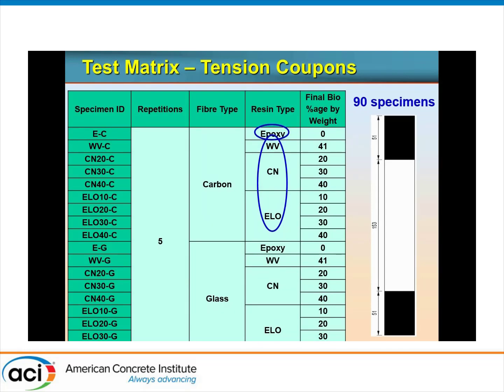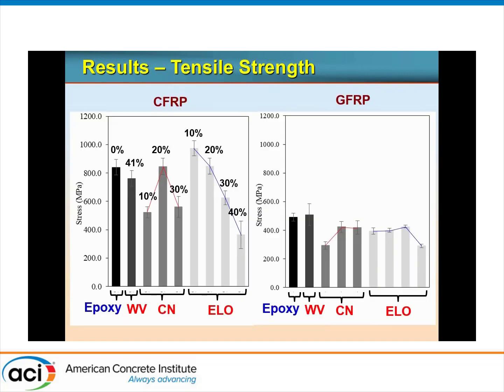So this is the test matrix for the tension coupons. We basically had the epoxy compared to the other three types of bio-based resins. For the second and third type, we varied from 20 to 40% bio for CN and 10 to 40% for the ELO. We also looked into carbon and glass, and we had 5 repetitions for the coupons. So we had a total of 90 specimens. These are the standard ASTM 3039, the typical tension coupons as we know it.